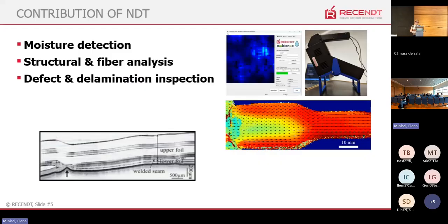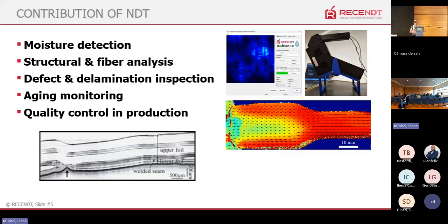One important thing is to avoid defects. We can directly detect defects with NDT methods, such as delamination or breaks in the samples, during the production line, and so reduce the waste. And also for long-time monitoring, to monitor the aging of bio-based or in general materials is really important to have an input on how long we can use it, when we should recycle it or change it. And a big point is also the quality control directly in the process or production line.